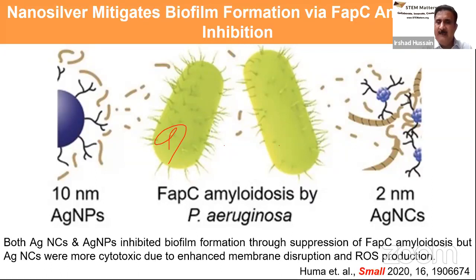And one of the phenomena that offers strength to this kind of biofilm is based on FAPC protein fibrillation. So FAPC protein, for example, can make fibrils that can give additional strength to the biofilm of bacteria. So we were trying to see how these nanoclusters of silver, which were 2 nanometer in size, and then silver nanoparticles, which were 10 nanometer, both having the same surface chemistry. They are coated with, for example, PEI. We were trying to figure out if they can inhibit the fibrillation of this protein, which is FAPC, that